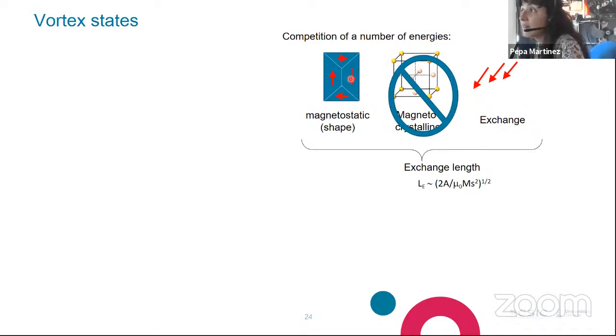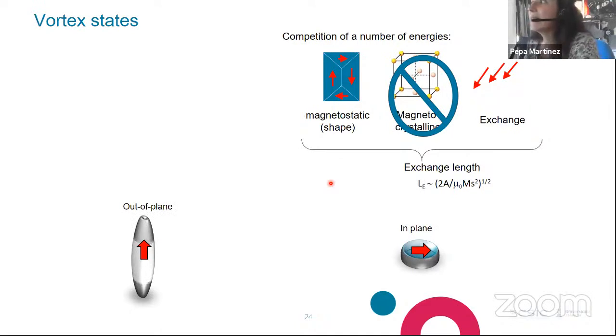But what happens when this magnetocrystalline anisotropy is negligible? Well, then the final state will be only given by these two main contributions. Of course, there are more contributions, but for understanding what I'm going to tell you next, these two are enough. Okay, in this case, you can very easily, intuitively understand what the ground state of a particle will be. If you think of a very long particle like being almost one-dimensional, you will have all magnetic moments pointing parallel to the axis of the particle, out of plane. Imagine a very large in-plane two-dimensional material, you will have all the magnetic moments lying in plane.